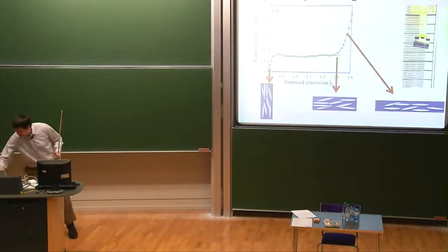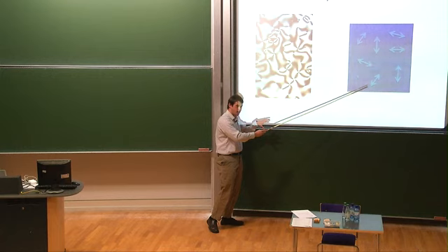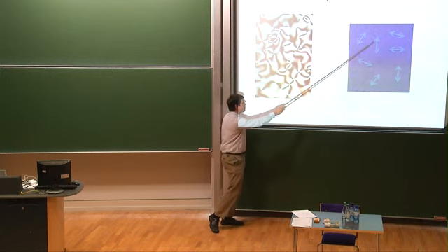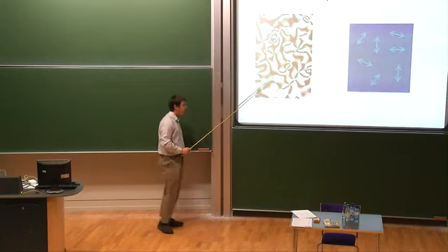Now, okay, so we know from liquid crystal liquids that we normally get these defect structures, which are certainly globally isotropic. And so sure enough, if you prepare your liquid crystal elastomer without due care and attention, you end up with a polydomain structure consisting of lots of little domains with liquid crystal order pointing in different directions, and consequently no macroscopic shape change when you go through the phase transition, because all the shape changes of domains are in different directions, and they in some sense cancel out.